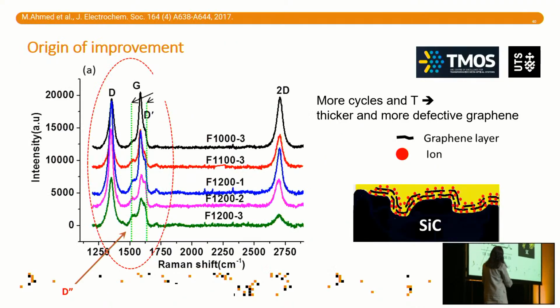Also, we found out that the best behavior was when we made quite a few layers, so 5, 6 layers of graphene, all with a certain type of edge defect. In this case, the problem is very different, because what we want is as much capacity as possible for the ions to intercalate the system. If graphene was a completely ideal layer with no openings, this would be really hard to make. It would be very slow. But this is very efficient, so quite a lot of layers with a lot of edge defects.